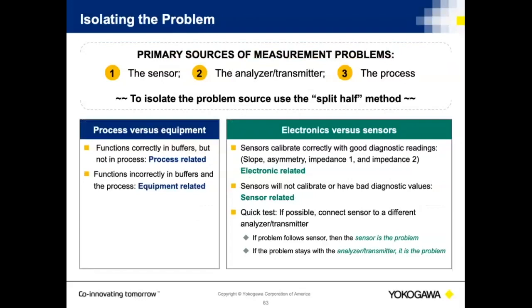You take the probes, you clean them up, you put them in buffer solutions. If they calibrate in buffer solutions and you have stable readings after you've cleaned and everything, then basically it's probably a process problem. If it goes the other way and you cannot calibrate, then it's probably your electrode set that's giving you issues. Which electrode do I suspect normally? I usually suspect the reference electrode is what's giving me problems.